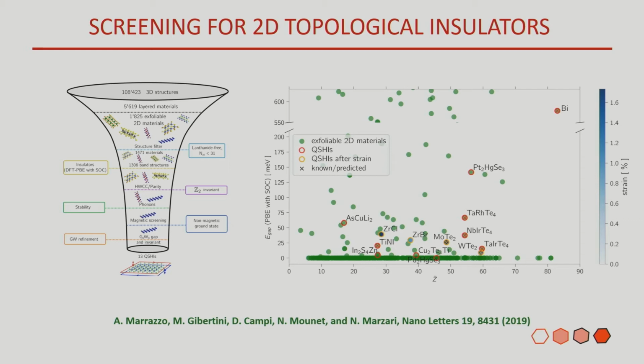And so out of all of this, most of the materials are green and boring, but the ones with the red circles are interesting. They are quantum spin Hall insulators. Some of them were already known, like bismuthene, but they are impossible to deal with experimentally. Some of them were already known, but have a comparatively small band gap. And there was something very interesting, never discussed, with a large band gap. That's very important for room temperature operation.